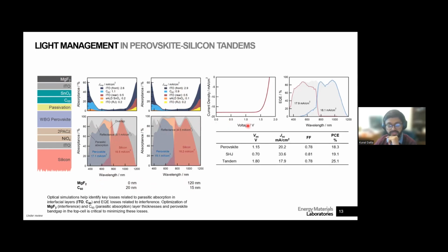And that allows us to make a tandem, which is at 25.1%. There's a bit of a voltage loss, but it's not significant compared to what's available in the literature. And most importantly, by this light management guided optimization, we can reach very good current matching between the two subcells. And so that basically means that we're not losing any current as heat, let's say.